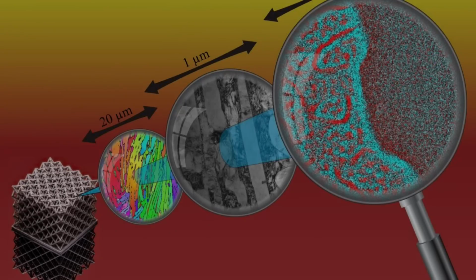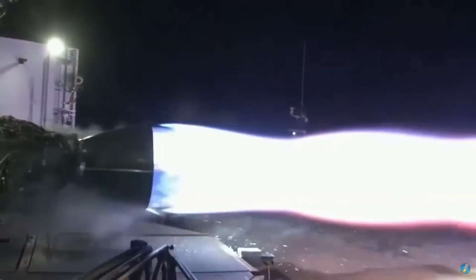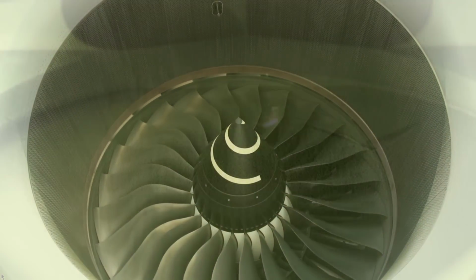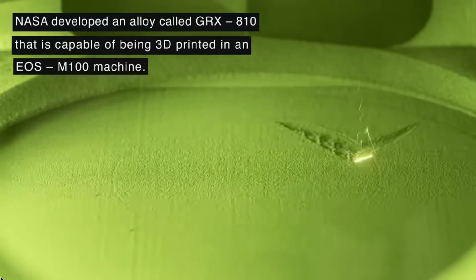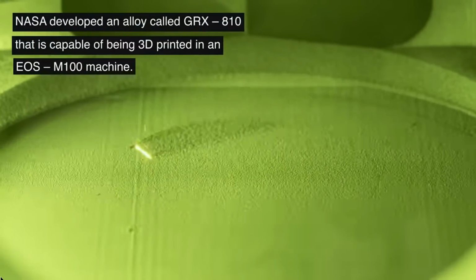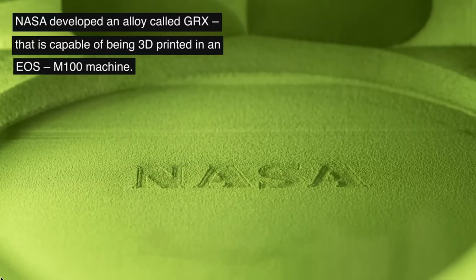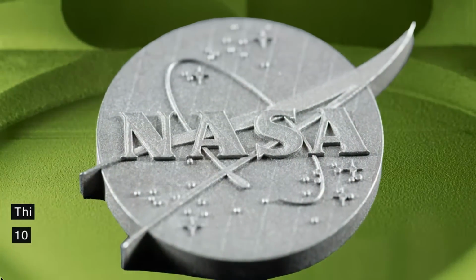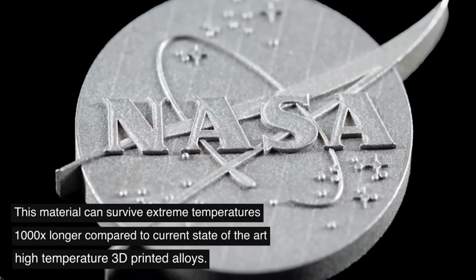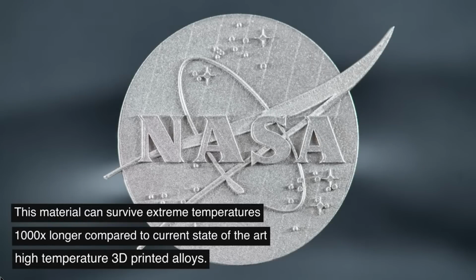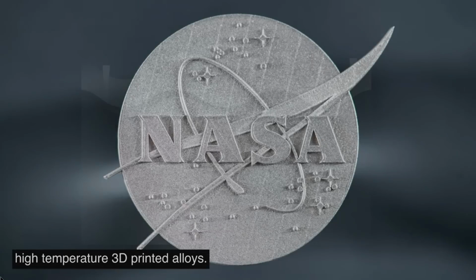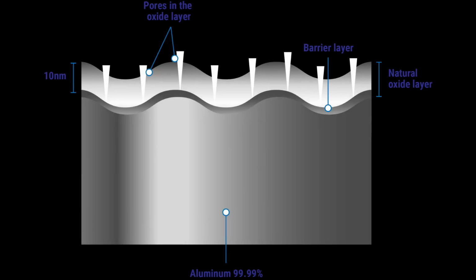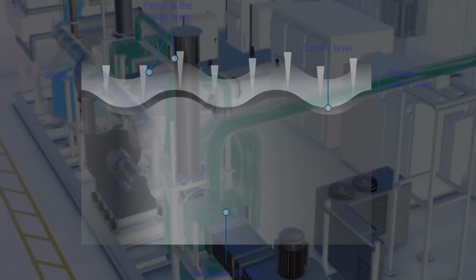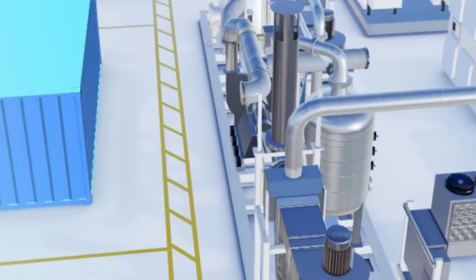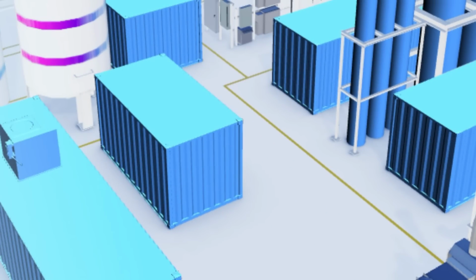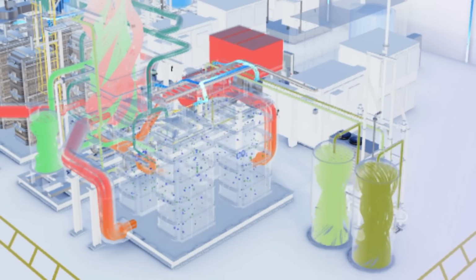temperatures, making them perfect for high-temperature, high-stress environments, like rocket and jet engines, but also for high-temperature efficient molten carbonate fuel cells, especially because the presence of oxide particles in ODS alloys also enhances their resistance to corrosion and oxidation. The oxide particles act as barriers, hindering the diffusion of corrosive species and protecting the underlying metal matrix from degradation. Think of it like the layer of aluminum oxide, also known as sapphire, that forms over aluminum metal, making it more resistant to corrosion. Fuel cells often operate in corrosive environments due to the presence of the reactive gases and electrolytes. GRX-810 demonstrates remarkable corrosion resistance, allowing it to withstand the harsh conditions encountered in these fuel cells.